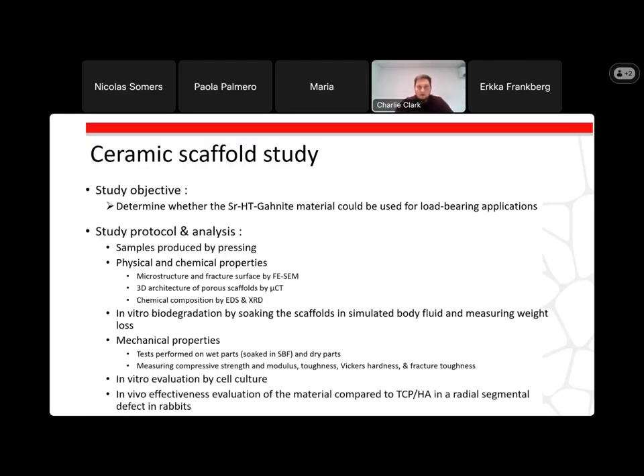So they actually conducted 2 different studies, which I'll be talking about here. One was on the material itself, so just on the powder. The objective was to determine whether the material could be used for load-bearing applications. So what they did is they produced some samples just by pressing, because obviously it's easier when you've got just the powder, and made some simple test parts. They tested the physical and chemical properties. They also did some biological tests in simulated body fluid. They then performed mechanical testing on some more complex parts. And then there were some more biological in vitro and in vivo studies that were conducted.